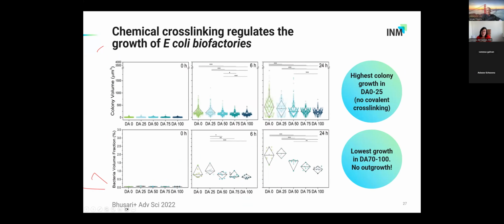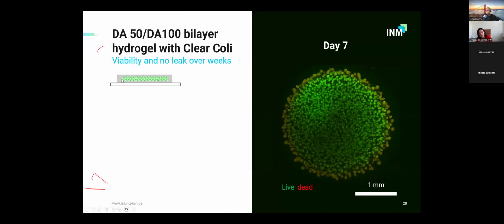If we do this in thin films and we quantify growth, this is what we observe. We observe the highest colony growth in the hydrogels with the lowest covalent cross-linking, and we quantify the lowest growth in the hydrogels with the higher cross-link, and we see no outgrowth, and this is important. That means we can generate, similar to what I told you about our gels, in our contact lenses, core shell composites or core shell materials in which we can leave the cells inside in one type of material and have the other type of material outside which contains the growth.